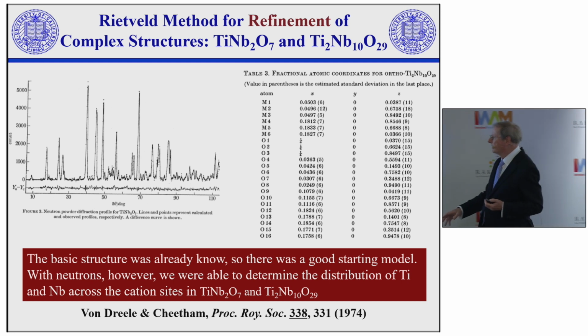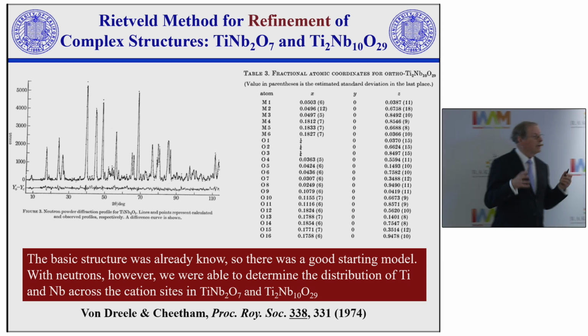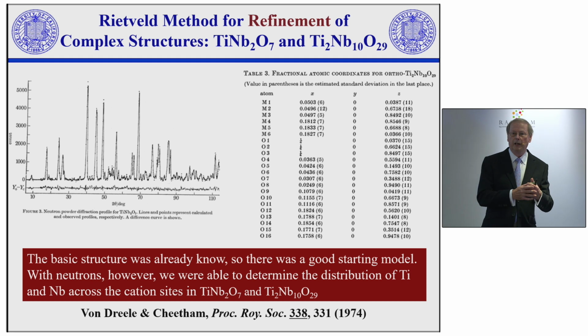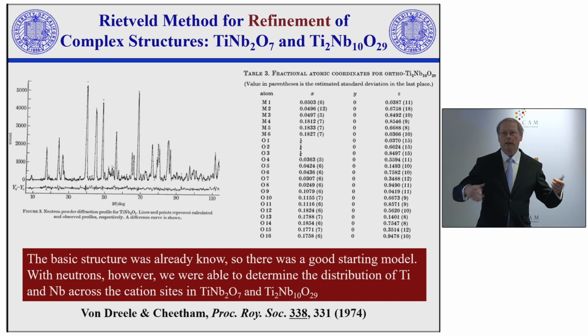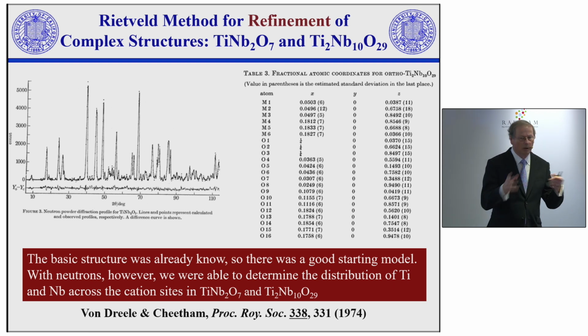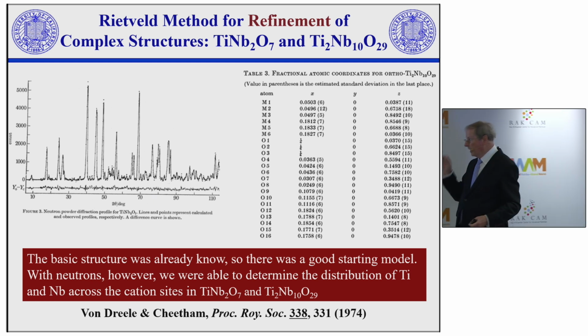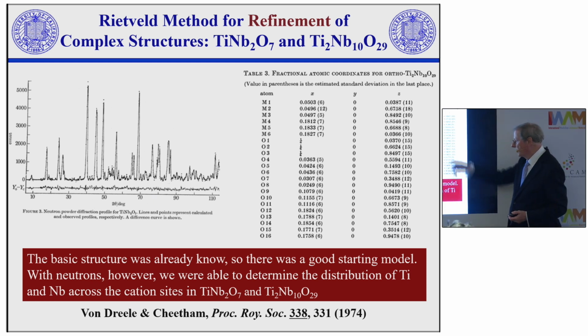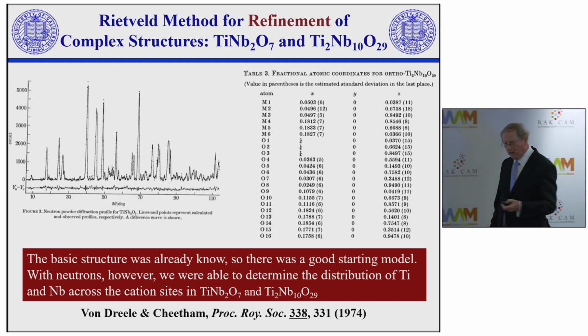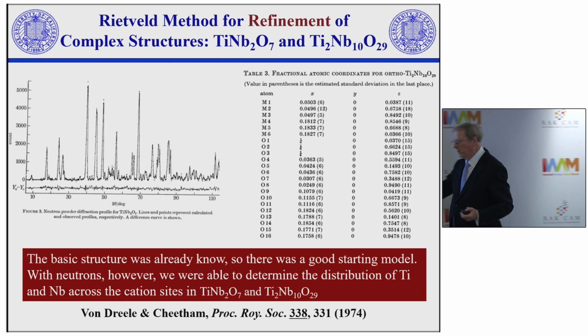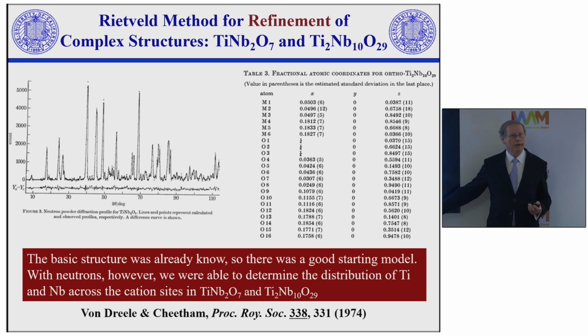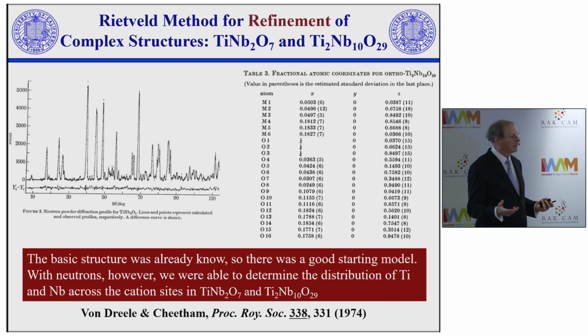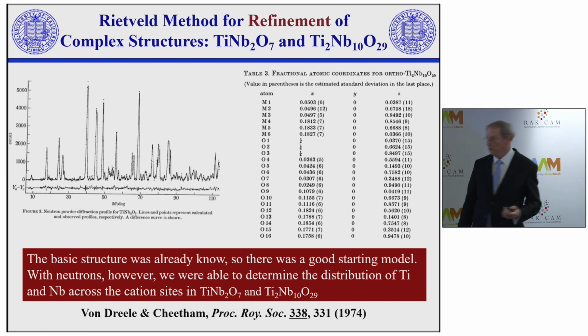And our interest in this was to demonstrate that this new Rietveld method was capable of refining an incredibly complex structure. And in doing so, we found that the titanium and niobiums were not at all randomly distributed, but they were segregated in different sites within the structure. And much later, that turned out to be important. So this was in 1974. We were not thinking of lithium-ion batteries because the lithium-ion battery hadn't been discovered or thought about at that point.